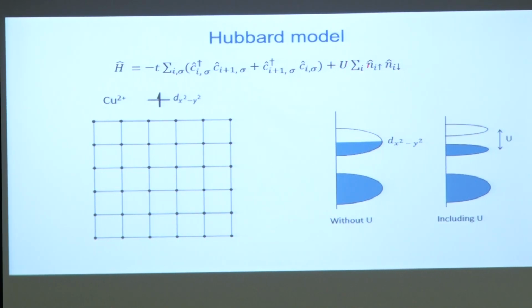So, if 2 electrons sit at the same site, which by Pauli's exclusion principle is allowed, because each orbital can take 2 electrons of the opposite spin. But because of the strong U, which does not let 2 electrons sit on the same site even if they have oppositely directed spin, your electrons will remain at their respective sites. They are not allowed to hop from one site to the other.